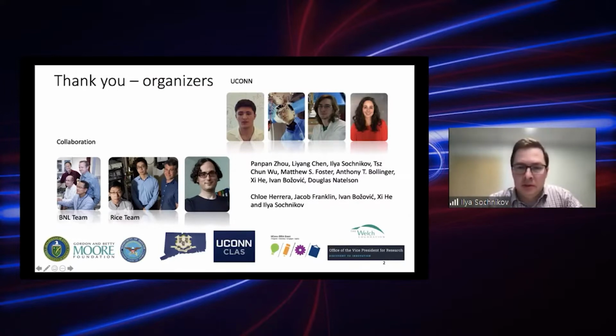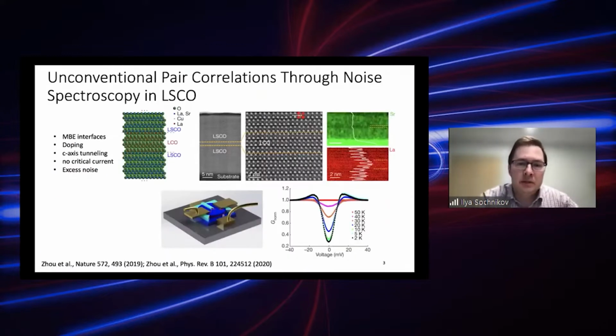They are listed here. The devices we're talking about here are LSCO, lanthanum strontium copper oxide, doped at different levels from underdoped to optimally doped. Then they are separated by a lanthanum copper oxide layer, which is undoped, of 1.5 unit cell thickness, and then another electrode of the same kind as the bottom electrode. They were patterned into Josephson junctions that are, let's say, 20 micron diameter circles with leads deposited on top and also contacting the bottom electrode. So these are C-axis tunneling devices, and the current goes through the insulating layer this way.